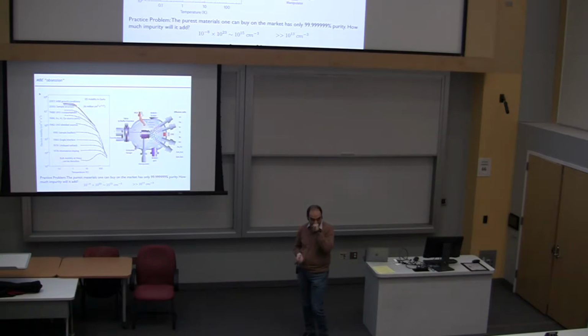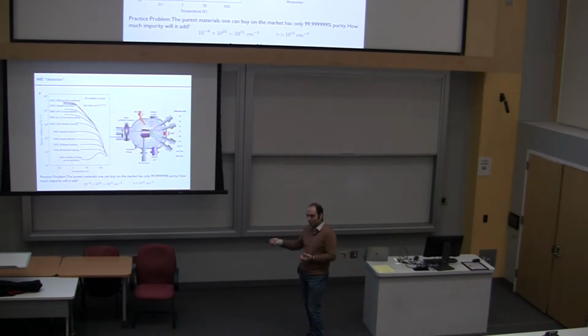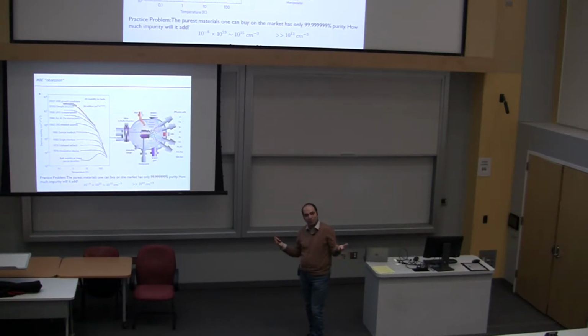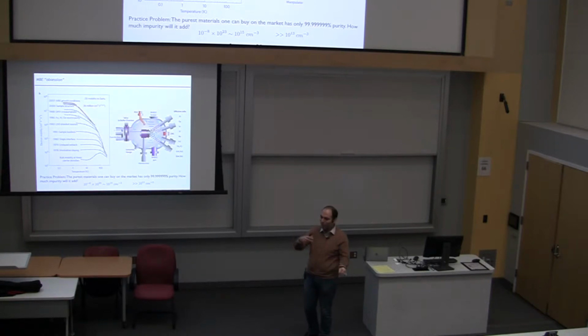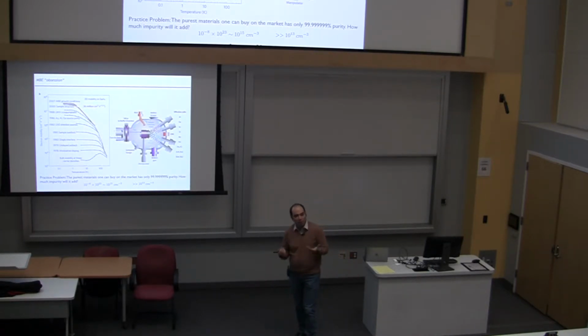That's actually a lot. In the best chamber, like Loren Pfeiffer's chamber, the background impurity is in the 10 to the 13, right? So even with that kind of purity, this is high, but not all of them incorporate. Depending on what material you put in the chamber, you can have a very high background impurity, just because we don't have pure enough material. People make their own zones that you evaporate and condense inside the chamber to get it better. But aluminum is very difficult. It likes to form bonds with other things. Some of them are easier, some of them are harder. But it's a difficult game.